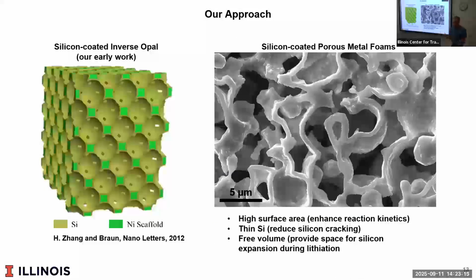So what did we do? This was sort of our idea: how about I make a foam? I make a metal foam and I coat the foam with silicon. Now when I charge and discharge, it goes in and out of the pores, but the whole thing stays the same thickness. It's pretty good, but our metal foam right now weighs too much. This is made out of nickel or copper. I need to figure out how to make this out of, say, aluminum, or even better, out of a polymer or something lightweight that will conduct electricity.